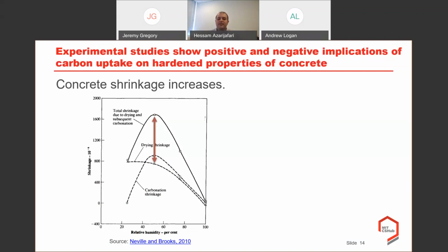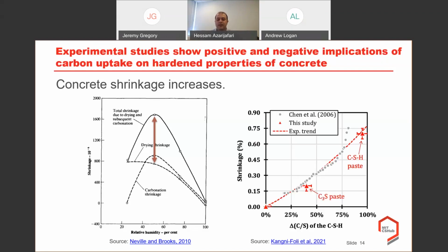Previously, it was perceived that the dissolution, the reaction of calcium hydroxide under the compression due to the drying shrinkage, will result in the formation of a stress-free calcium carbonate. So this is stress-free, as opposed to that compressed calcium hydroxide, which will increase the shrinkage. But now recent studies and many different historical studies show that it's more related to the decalcification of the mixture. Here on the x-axis, you can see the ratio of the calcium to silica, reduction of the CSH, the calcium silicate hydrate, and here is the shrinkage. And as you can see, when we have a more significant drop in the calcium to silica ratio, we have a more significant shrinkage as a result of the carbonation process.